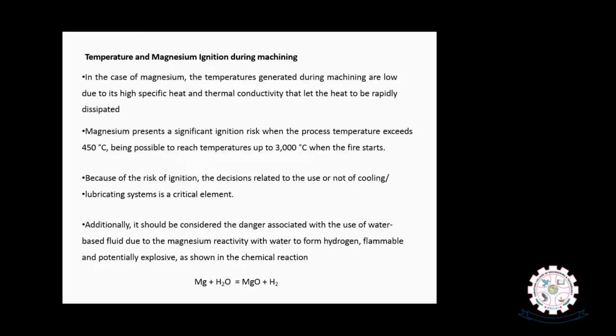But the challenge is, in case of magnesium, the temperatures generated during machining are low due to its high specific heat and thermal conductivity, which lead the heat to be rapidly dissipated. Magnesium presents a significant ignition risk when the process temperature exceeds 450 centigrade. So while machining magnesium, selecting the coolant is crucial. Even without coolant we can machine magnesium, because the heat dissipation capacity for magnesium alloys is very, very high compared with steels and aluminum.